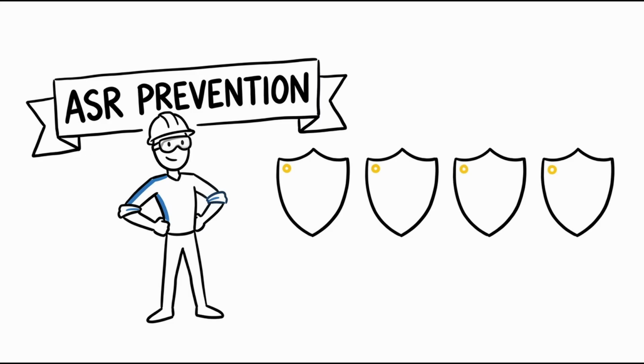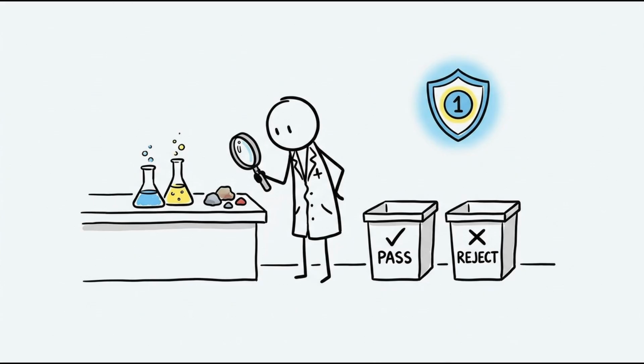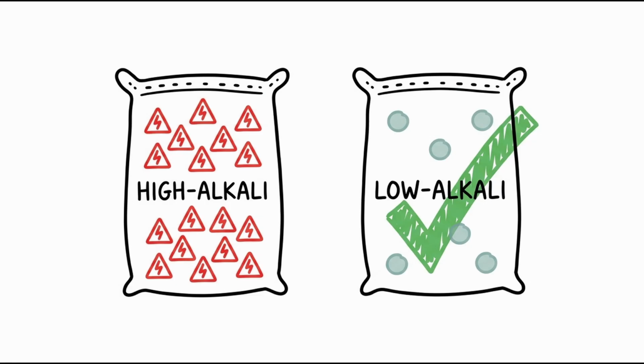The good news, ASR is entirely preventable. If you catch it before construction, not after. Defense number 1. Test the aggregate source before you ever build with it. Standardized lab tests can identify whether a particular quarry's stone contains reactive silica minerals, essentially screening candidates before they're allowed anywhere near a road mix. Defense number 2. Use low-alkali cement. If the alkalis simply aren't present in large enough quantities to begin with, the reaction has far less fuel to work with, even if the aggregate is somewhat reactive.